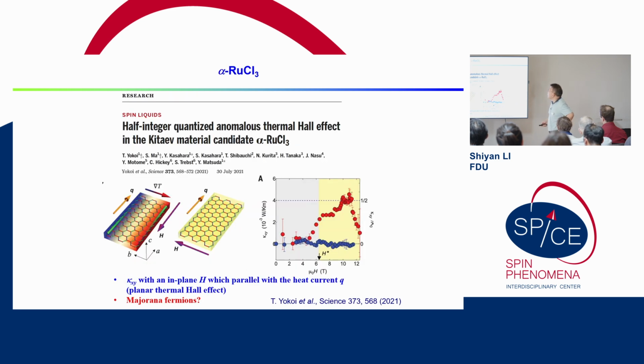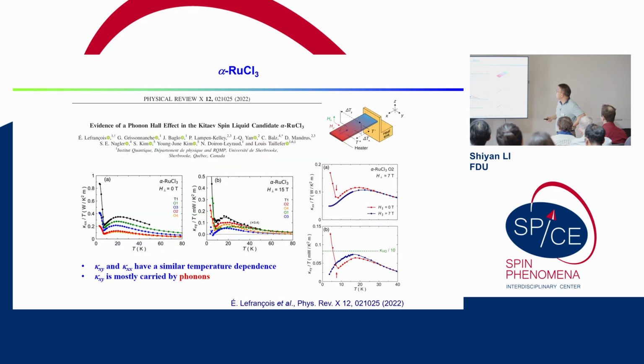Okay, so this planar thermal Hall, I skip it. We also put the field perpendicular to the plane, so it's a conventional thermal Hall effect. They have similar temperature dependence, so the conclusion should be that it is mostly carried by phonons.